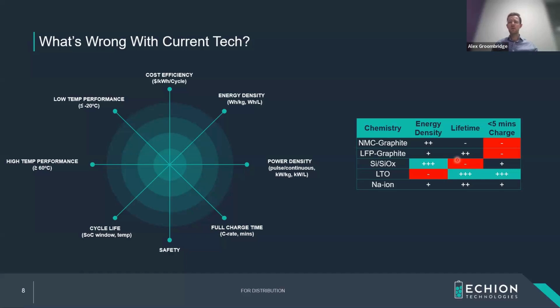LFP graphite is then quite interesting and is in use for some of these trials. Has a decent lifetime, enough energy density, but its chargeability and operation at high temperature become a bit of a challenge. Lithium titanate is very attractive for lifetime and for fast chargeability, but has a limit on energy density and a high cost. Sodium ion is then sort of similar in this LFP graphite space, but of course there's a number of other challenges relating to it. So where does niobium come in? And what am I talking about?